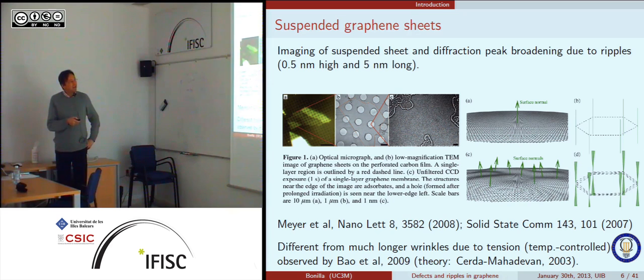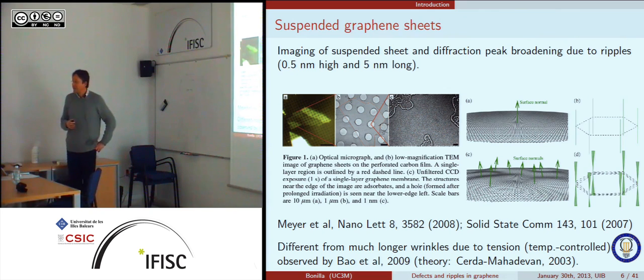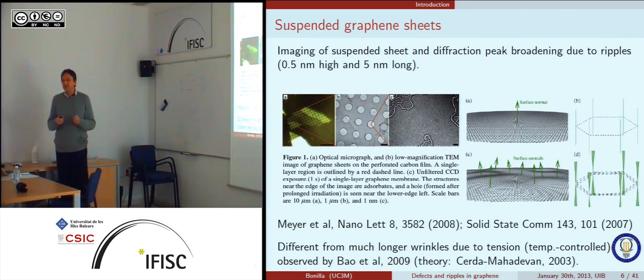Now, the other thing that people discovered immediately was that there are ripples in the graphene. So these are the reciprocal lattice vectors. If this is a plane, this would be perfect lines perpendicular to that. What they saw were diffraction spots that, if you tilt the microscope, you see that they stay more or less where they are. That's a sign that it's a monolayer, otherwise you'd see other things.